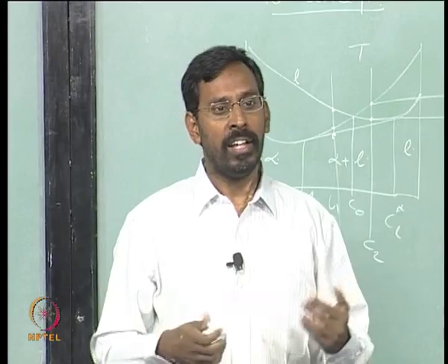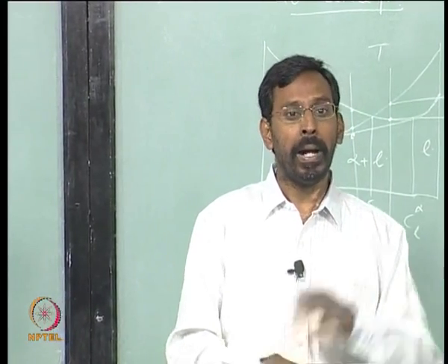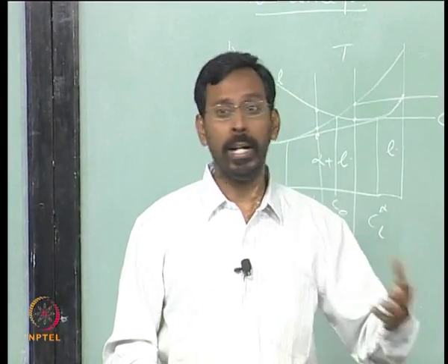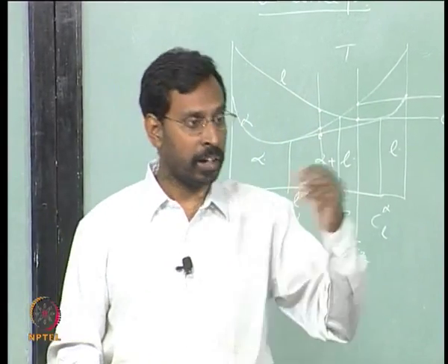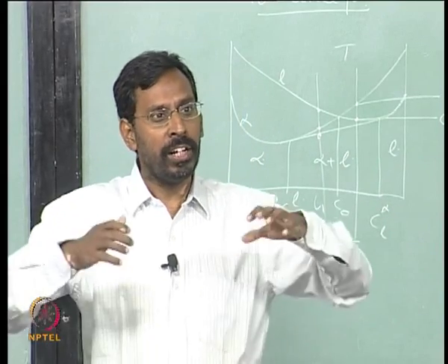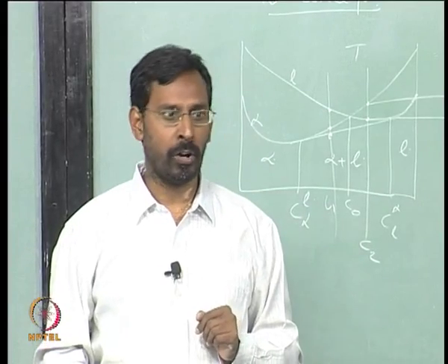So, he says if I can somehow reduce these foreign particles by making the liquid droplet smaller and smaller, the probability of finding a foreign particle reduces. So, he did some kind of an atomization of the liquid droplets.